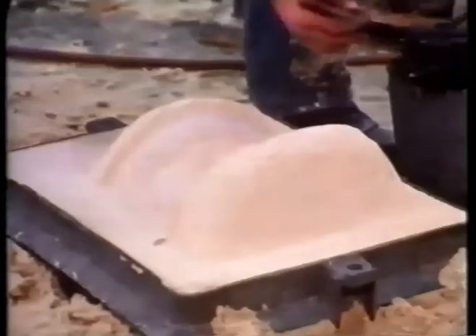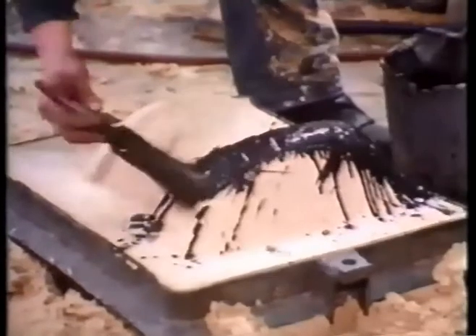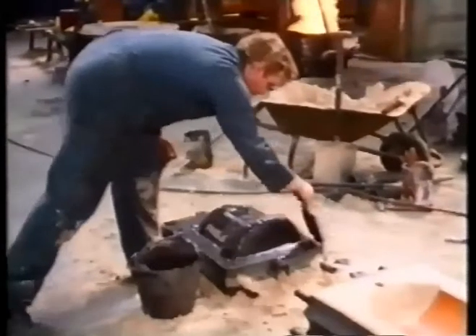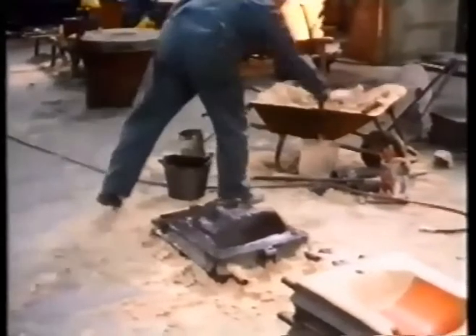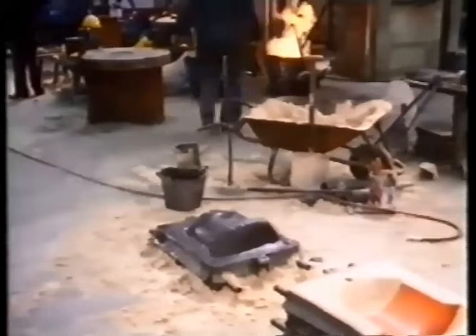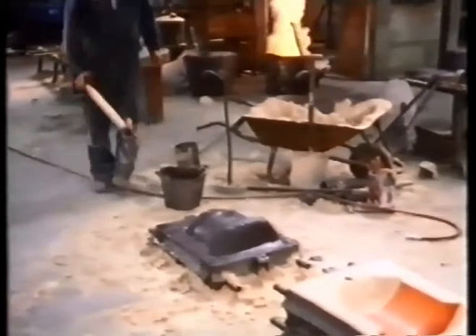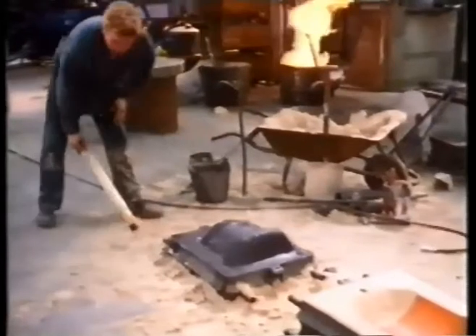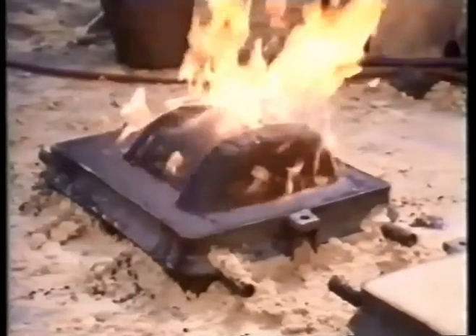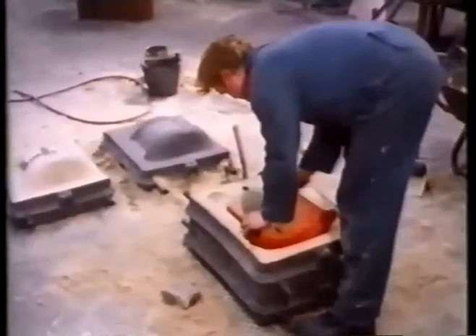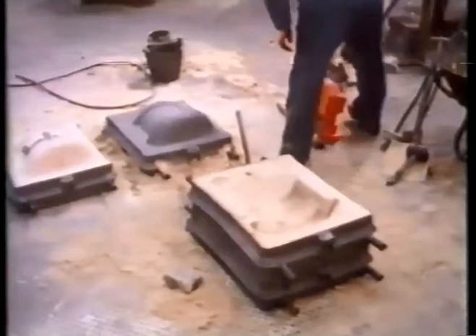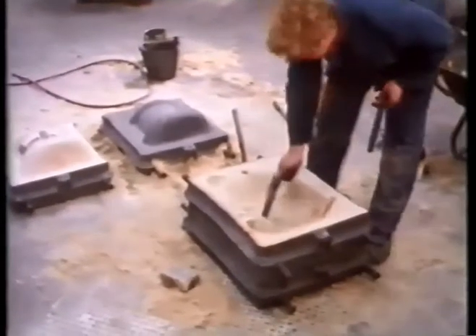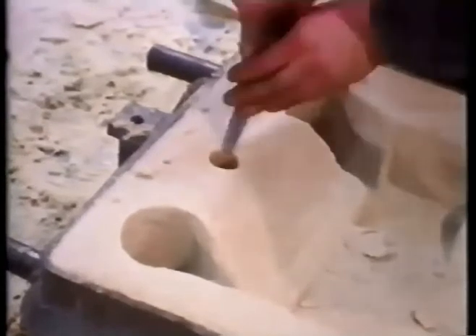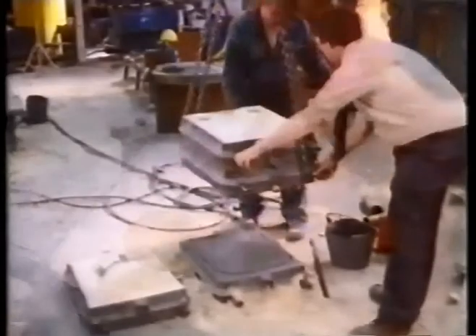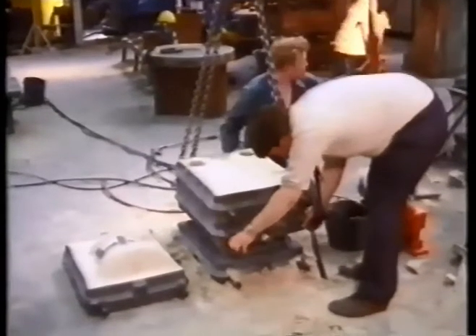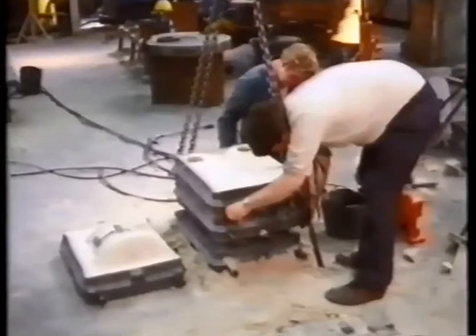The inner surfaces of the mould are coated with a mould wash. This improves the surface characteristics of the mould and prevents the molten metal from penetrating between the sand particles or eroding the sand during the pour. The organic solvent in the mould wash is burnt off to leave the mould quite dry. The wooden pattern is then removed from the top half of the mould and an ingate is carved. Once the mould is washed, the top half is put back onto the bottom half to complete the sand mould assembly ready for pouring.